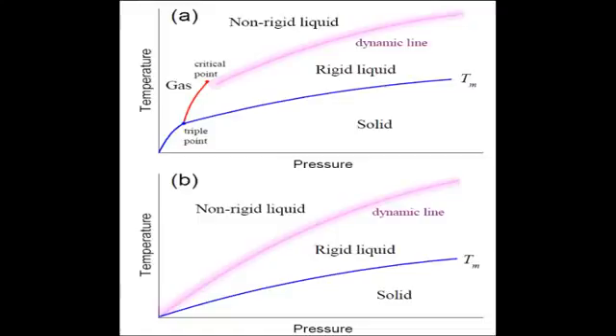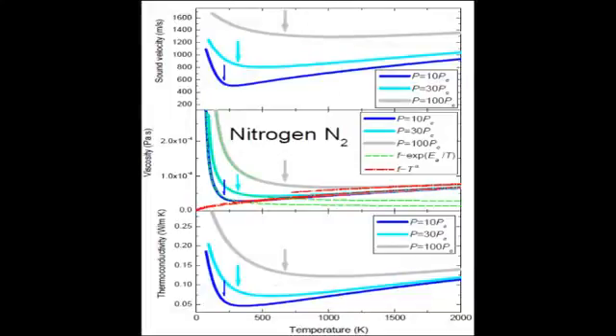We analyze the new line theoretically, as well as in real and model fluids, and show that this line corresponds to the qualitative change of most liquid properties. Here you can see the qualitative change of the temperature dependences of sound velocity, viscosity, and thermal conductivity of liquid nitrogen at pressures 10, 30,